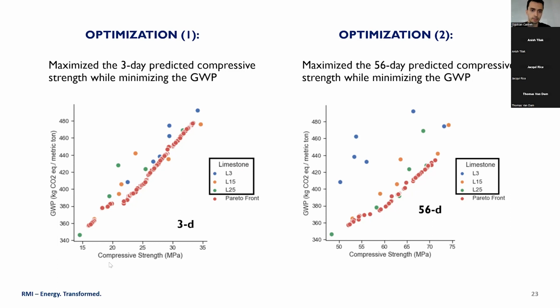The data points are colored differently with respect to the limestone particle size. L3 means 3 micrometer median particle diameter of limestone, and similarly for the others, L15, L25, they are coarser. The red circles show the Pareto front, which is the non-dominated, the best solutions reaching the objectives of high compressive strength and low global warming potential. And from the trends, the algorithm came up with these LC3 compositions, the so-called Pareto fronts.